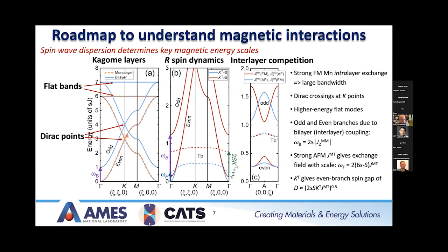So these manganese magnon bands feature these Dirac points here at the K points, at momentum transfers corresponding to the K point for the kagome layers. And then you also expect to see these flat magnon bands up at much higher energy. We predict this energy scale to be up near hundreds of millielectronvolts. Okay, so the center panel here again shows the splitting between the even and odd bands. And then it also shows where you expect to get bands due to the rare earth atoms. So in this case, terbium.